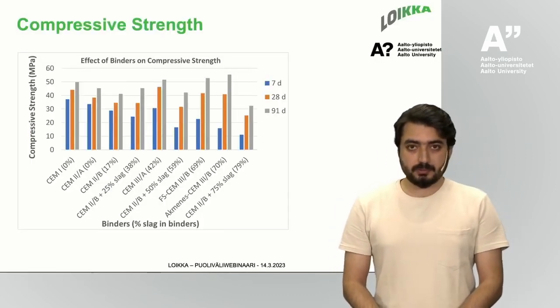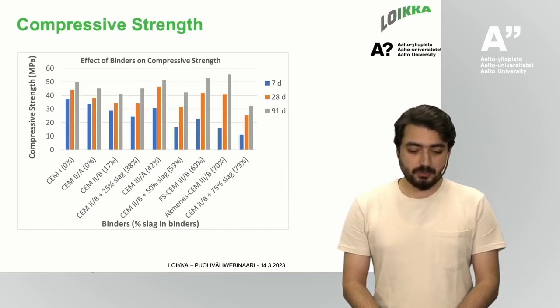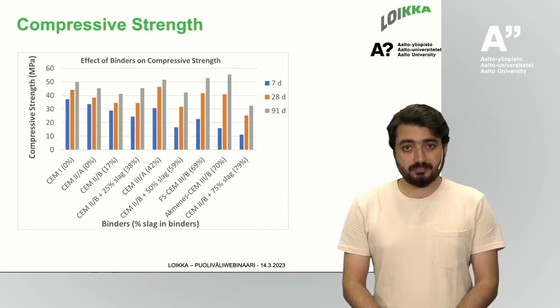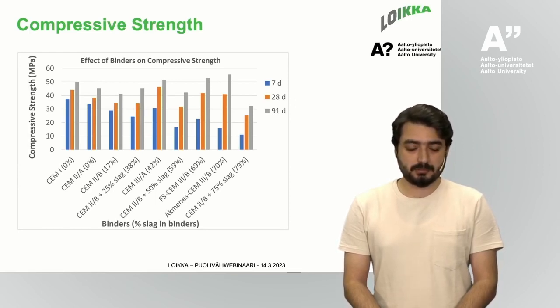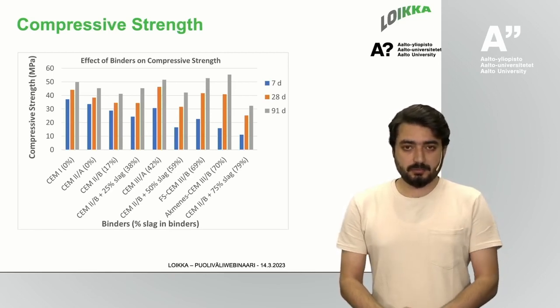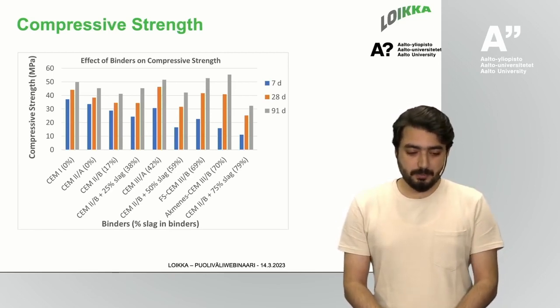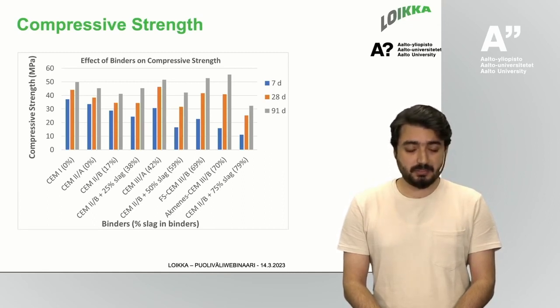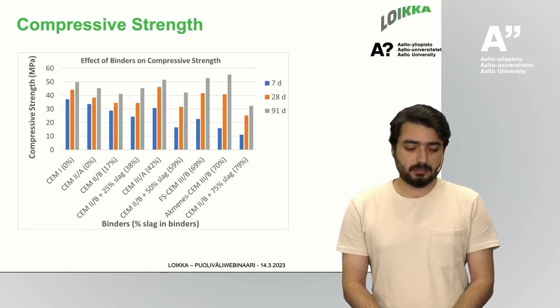So, moving on with the results that I received. For compressive strength, overall in this phase we used 9 different binders with different slag contents, in an incremental way from 0 to almost 80%. If we look at the graph closely, starting with the blue ones, which are 7 days, it shows that when the slag content is increasing, the initial compressive strength is decreasing. So it means that the slag is lowering or delaying the hydration process.